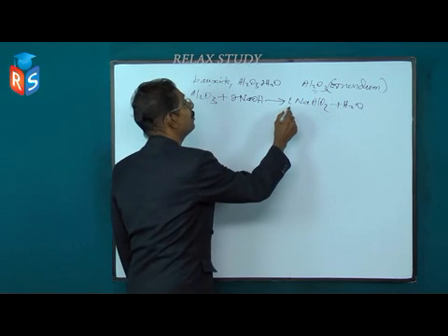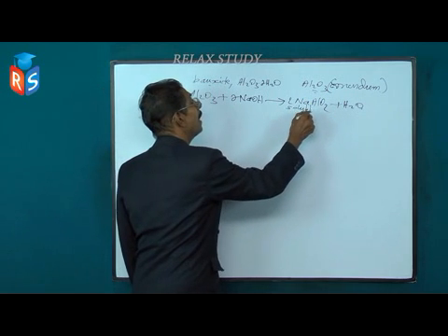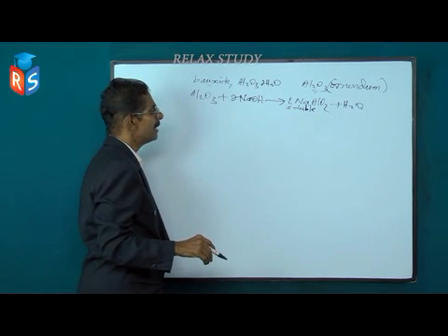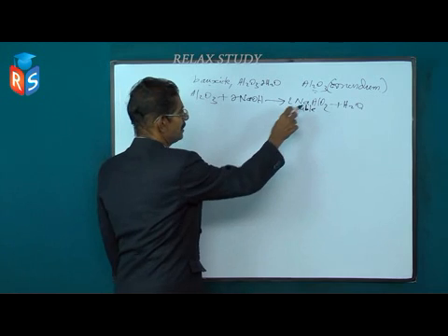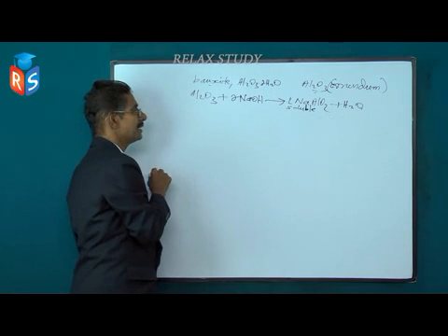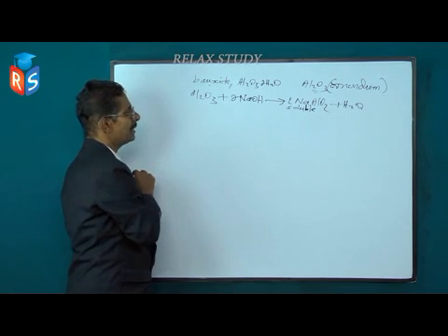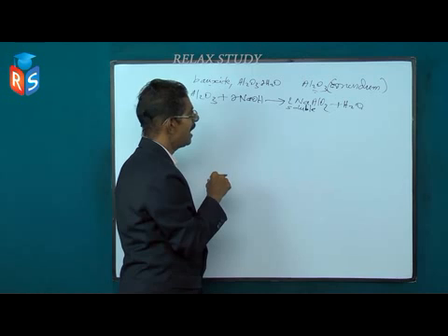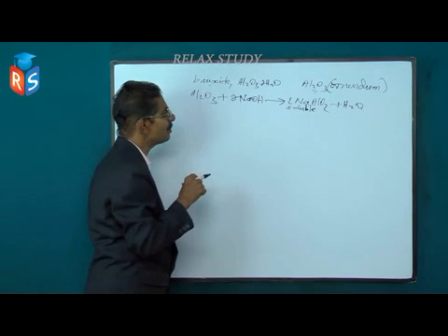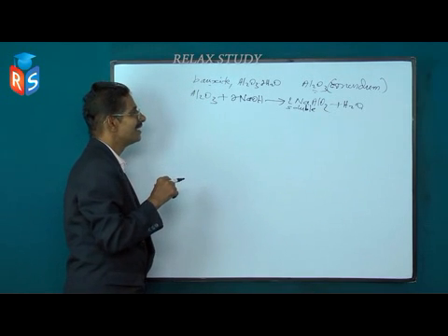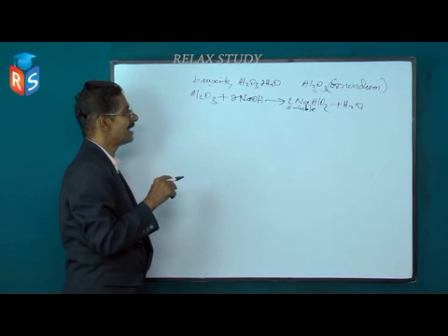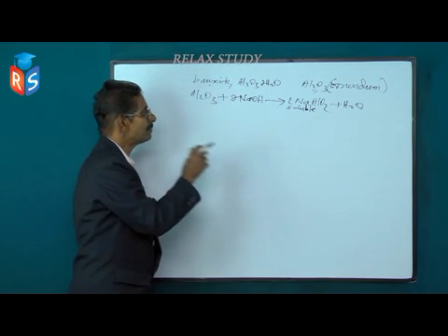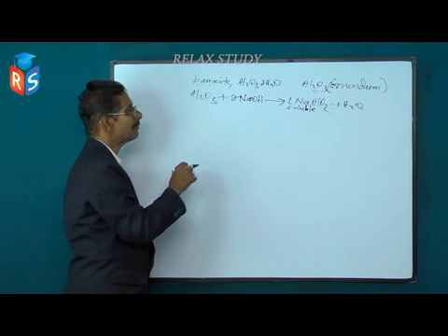NaAlO2, sodium aluminate, is soluble in water. Obviously, you can filter off the undissolved impurities. Now, this solution of sodium aluminate is treated with more water, agitated, and a little aluminum hydroxide precipitate is added. The process is called seeding out, to bring out the major part of the aluminum as aluminum hydroxide.